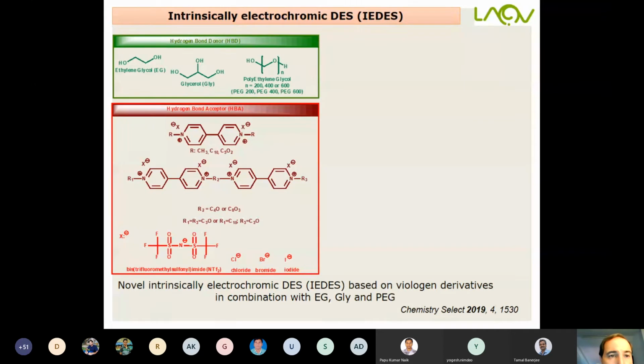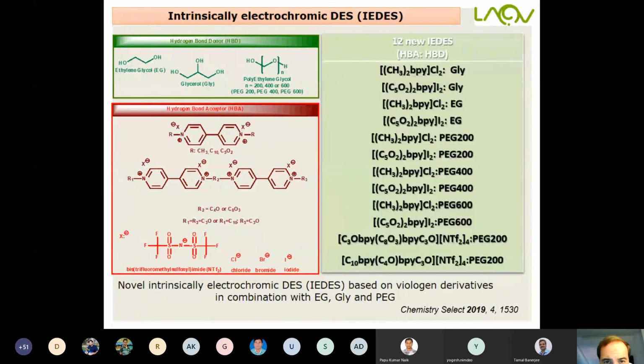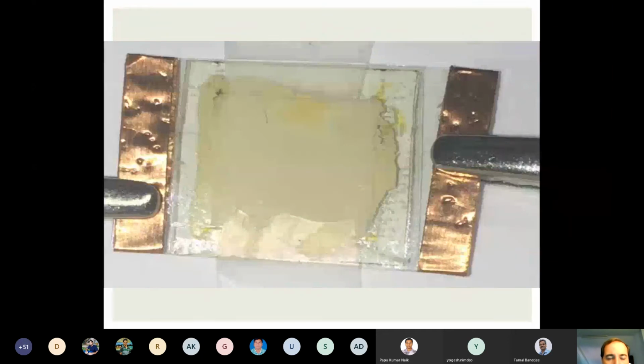But it's possible to prepare intrinsically electrochromic deep eutectic solvents. This means not only as electrolyte, but also as electrochrome, as we already proved for ionic liquids. And we developed 12 new intrinsically electrochromic deep eutectic solvents in different combinations, and these are based on viologen derivatives in combination with ethylene glycol, glycerol, and polyethylene glycol, and they work as intrinsically electrochromic deep eutectic solvents. I can show you here a system.